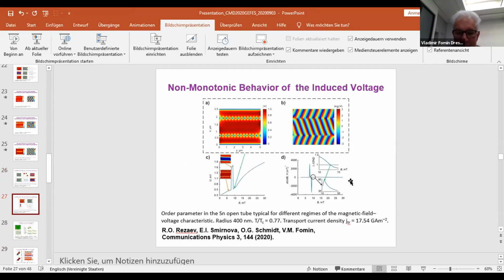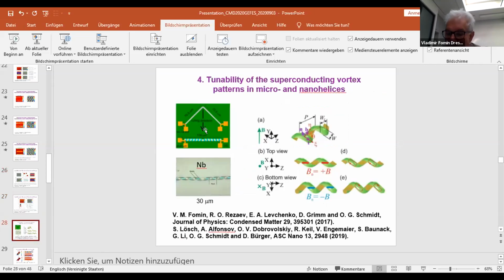Similar calculations were performed for another material, for tin, and then the same peak occurs at lower temperatures shown here. So it's all material dependent, but robust. Taking into account that my time is almost over, I will very briefly go to the micro and nano helices which were fabricated both by self-rolling and by ion deposition. The examples are shown here.